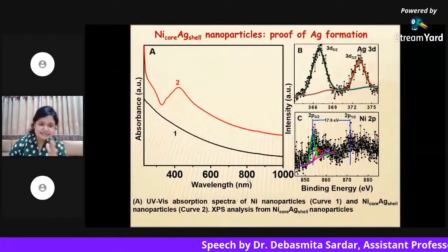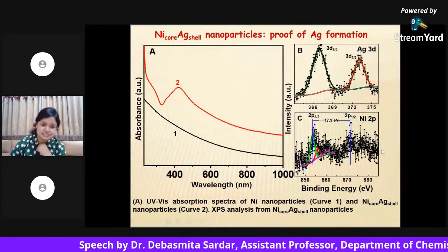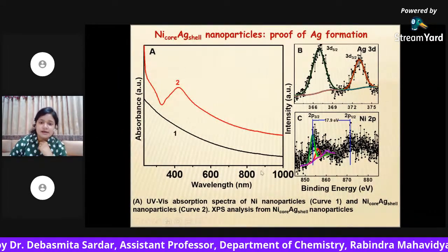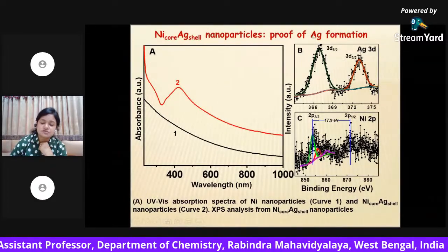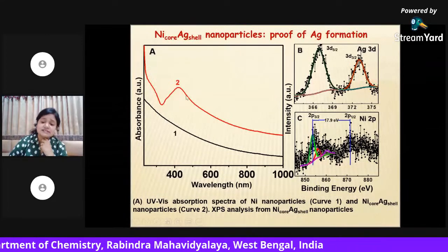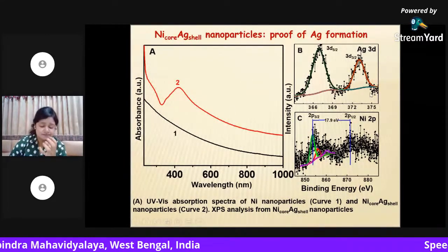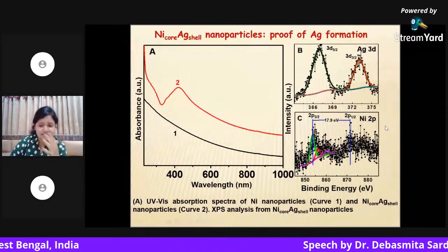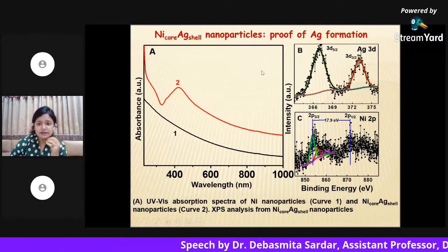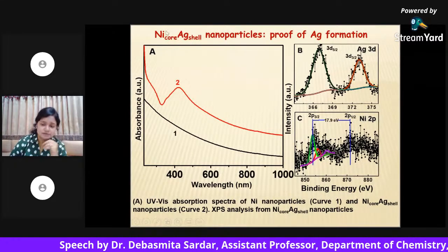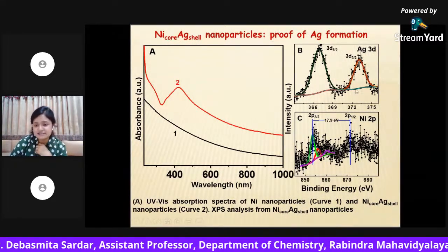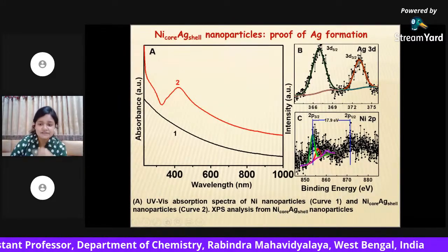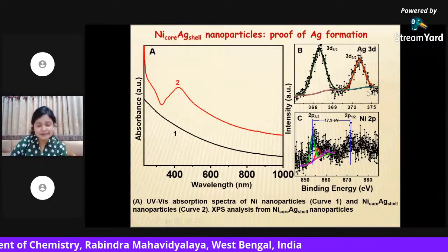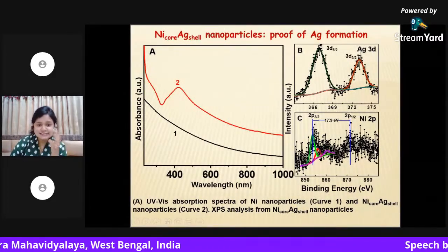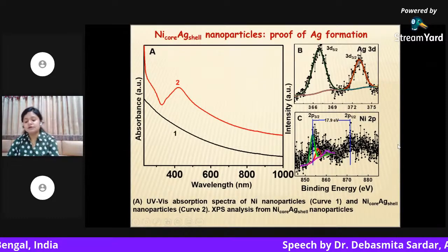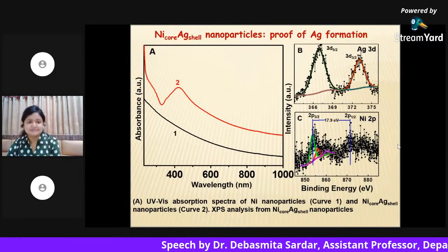So this is the nickel silver nanoparticles characterization. This is UV visible spectroscopy, and this is XPS spectroscopy. From XPS, I told you earlier that XPS spectroscopy depicts the surface characterization, the surface property. In surface property, basically these types of nanoparticles are core shell nanoparticles. So on the surface there is silver. The presence of silver can be proved by these characterizations. So these types of characterizations are very useful to characterize nanoparticles.